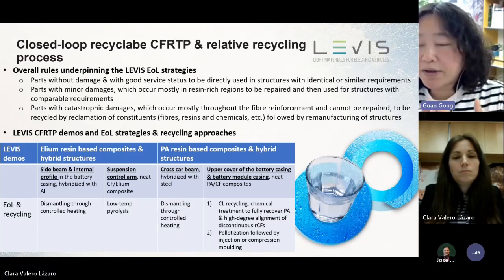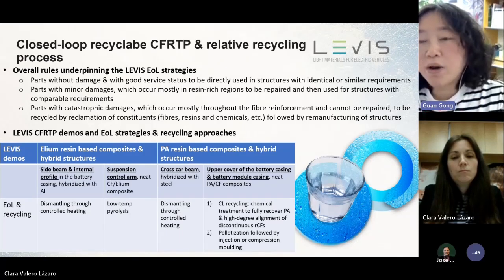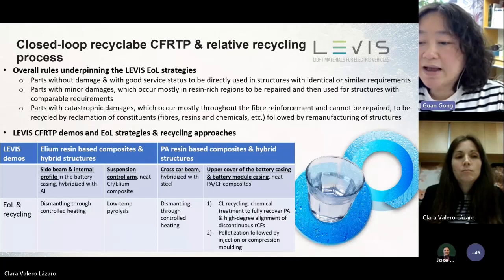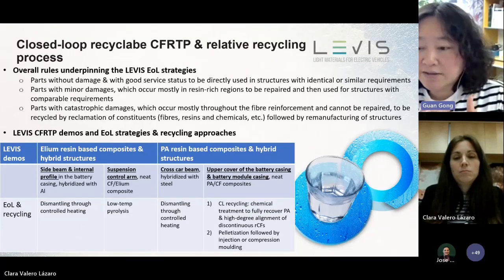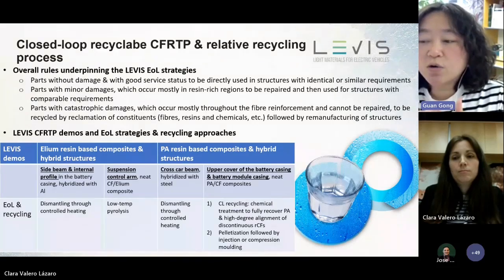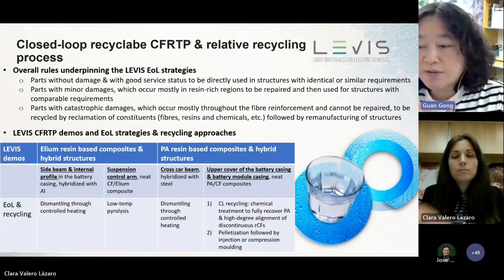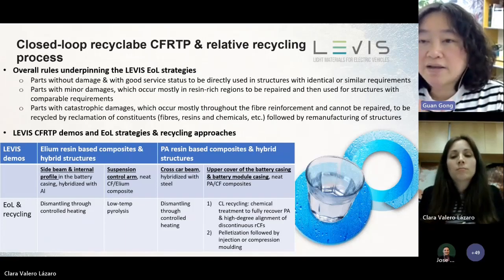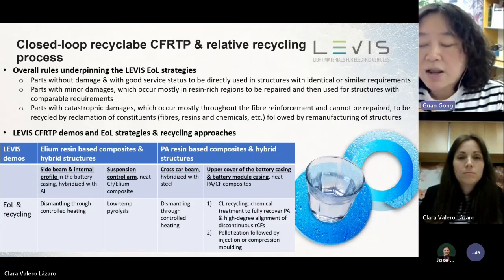However, those components can be categorized by the thermoplastic matrix and by the design, whether they are neat carbon fiber reinforced thermoplastic composite or hybridized with metallic parts. So based on this classification, we can see that there are two types of thermoplastic matrix in the Levis project. One is the aliphatic polyamide, PA6 and PA66, and the other one is liquid thermoplastic Elium resin, which is based on methyl methacrylate. Some of them are neat polymer composites, and some others are hybridized with either aluminum parts or steel parts. So next slide, please.